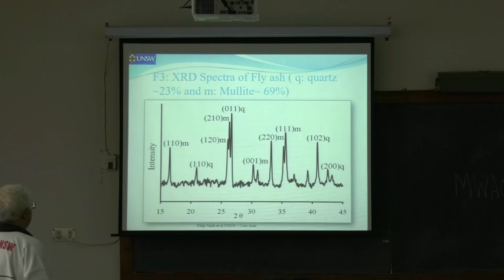This is the XRD spectra of fly ash. You have intensity versus 2 theta, all right? And these are quite common things. So you get the peaks that reflect the kind of crystallinity. Q stands for quartz and M for mullite. They are the components of the fly ash. So you can get all these peaks, and these peaks actually identify the materials present there.